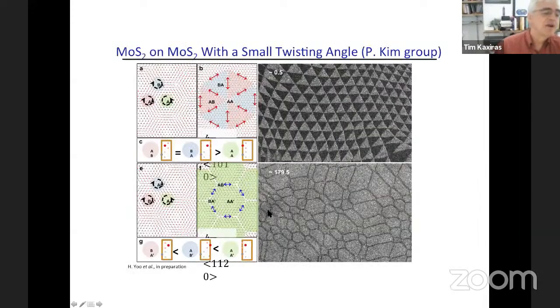So we have done lots of calculations of similar type for other systems. So this is molybdenum disulfide with a small twist angle, also from the Philip Kim group. Different patterns here for different orientations. Near the 0-degree orientation, near the 180-degree orientation. Those are the 2 low energy configurations for this material.